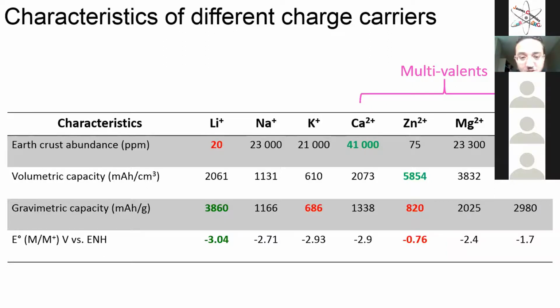Fortunately, there are other alternatives. We are talking about sodium, potassium, or other multivalent metals, because with lithium you have only one charge. With calcium, magnesium, or aluminum, you have two or three charges. So during the same redox reaction, instead of one electron, you can store two or three electrons. And this will give you access to high energy density. Another very important factor is the volumetric capacity, which matters for electric vehicles. And aluminum here provides a high volumetric capacity.